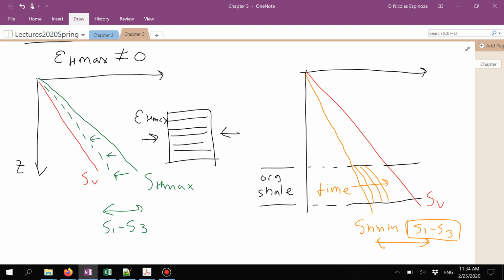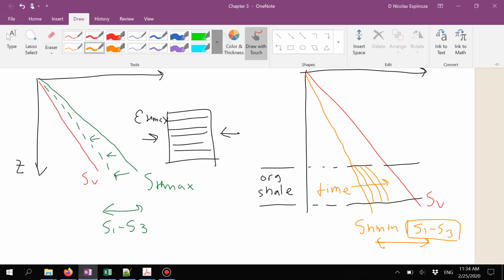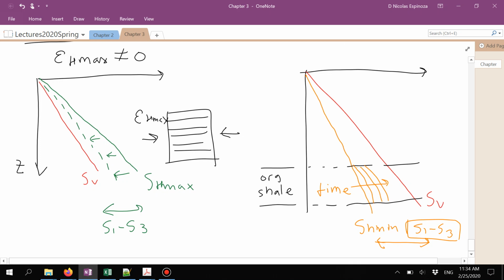And this is quite important because now we can see that probably some of our models that predict stress just based on elastic properties, if we're not considering this viscoelastic component, might be wrong. And there are recent studies that show that this is actually real behavior. Stress in some of these organic shales that exhibit quite a bit of viscoelastic behavior tends to have a horizontal stress which is much higher than what you would predict without this stress relaxation.